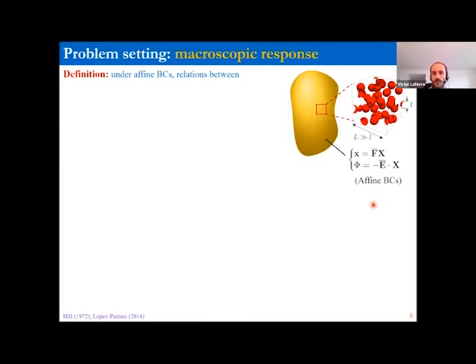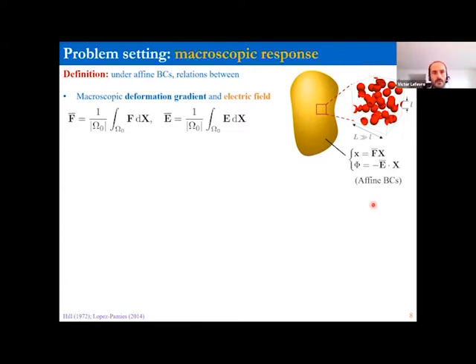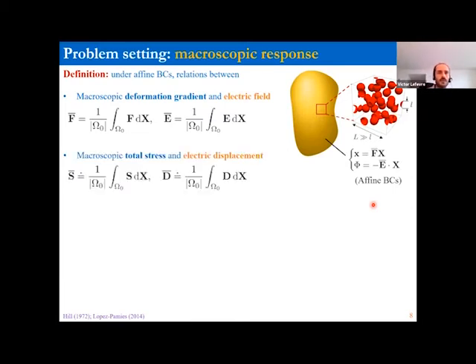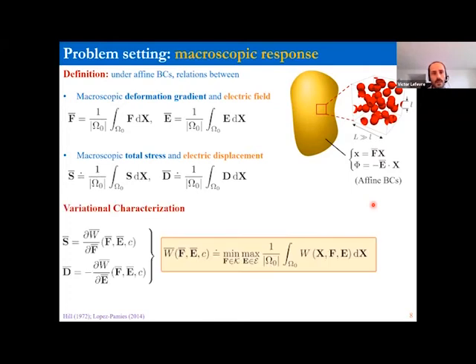It's not difficult to show that F bar and E bar that we prescribe are actually the volume averages of the local deformation gradient and the local electric field. And these are the macroscopic deformation gradient and electric field. So we can define the macroscopic total stress S bar and electric displacement D bar as the volume averages of their local counterparts. And this macroscopic response that we're after for these composites can be written in this way as these two partial derivatives of this quantity W bar that is solution of this variational problem here.